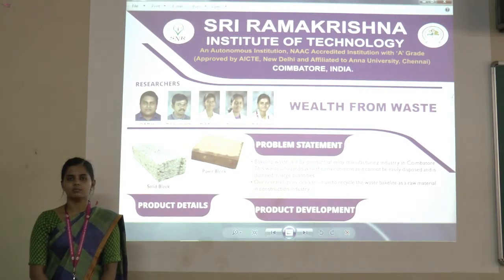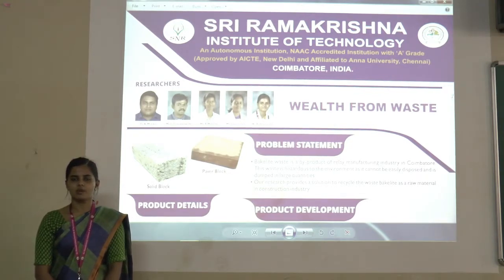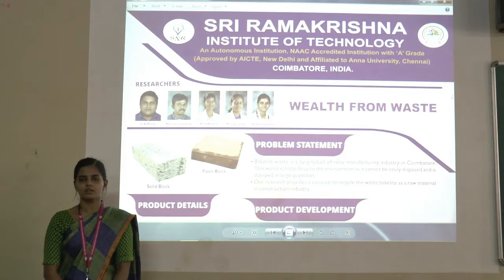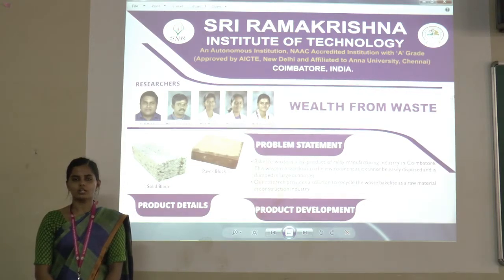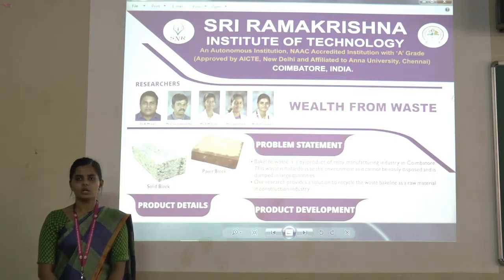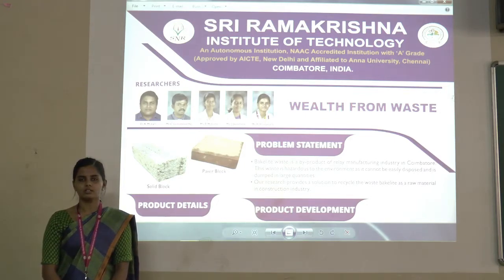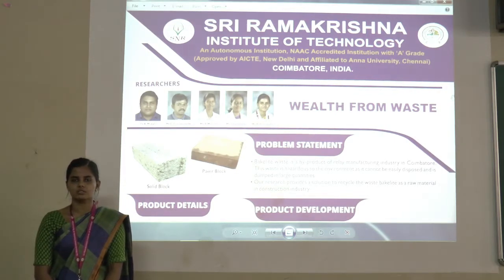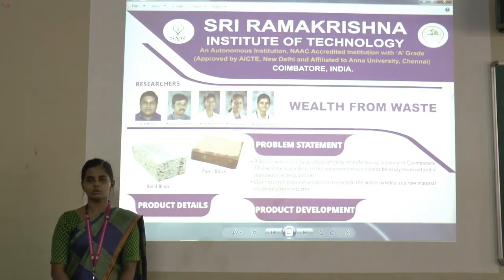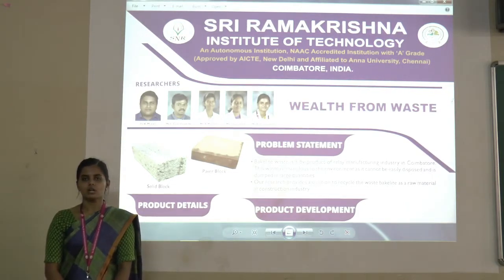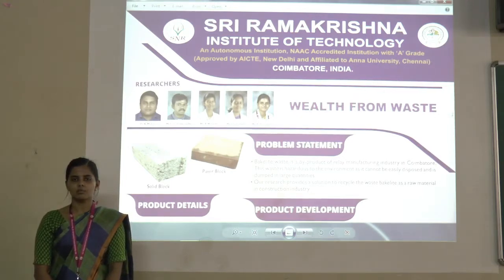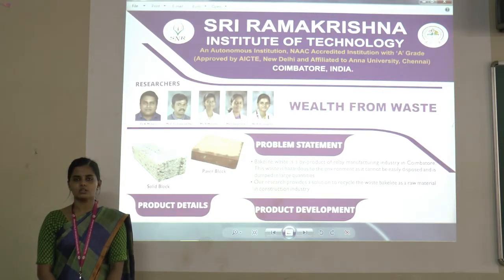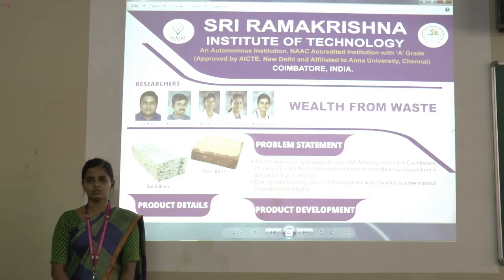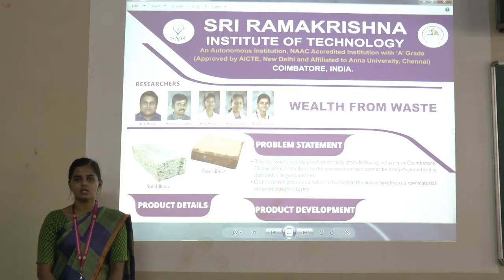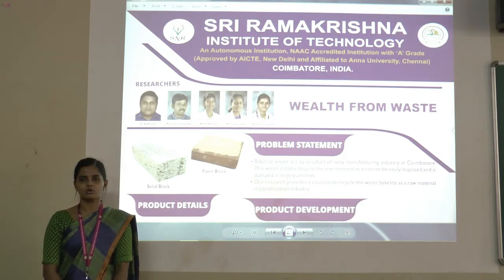Our next product is solid block using partial replacement of Bakelite. In this product, we are going to evaluate the strength of concrete and the solid blocks. We are going to make the product with various percentages, that is 0%, 5%, 10%, 15, 20, 25 and 30%. We are going to evaluate the strength of concrete by using the compressive test. The compressive test values have been taken at the end of 7, 14 and 28 days. The dimension of the solid blocks used here is 380 by 150 by 150 mm.